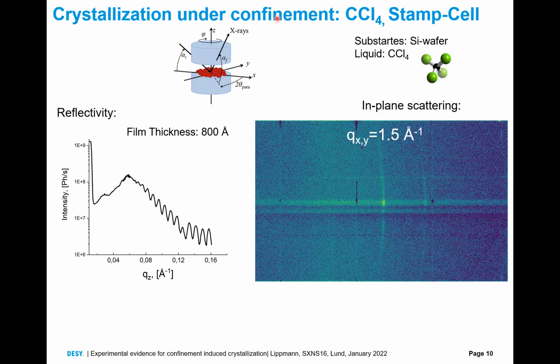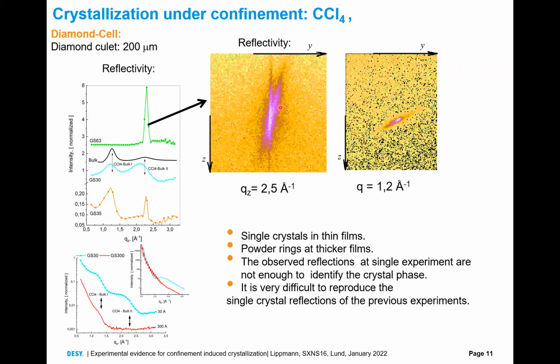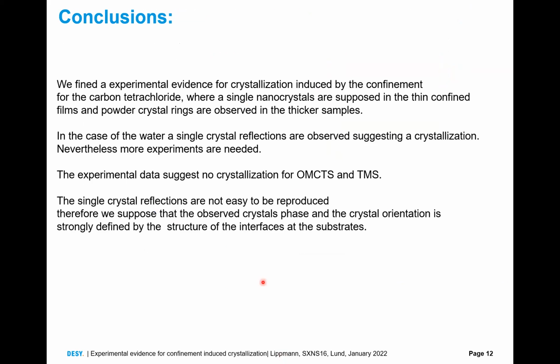About the carbon tetrachloride, we have studied this extensively, and we found out that it crystallizes in rings if we have thick films. It crystallizes in powder if you have thick films. And in the case of thin films, we observe single crystal reflections like in the case of water. With this, I come to the conclusions that we are pretty convinced that carbon tetrachloride can crystallize in confinement. In the case of water, we also observe single crystal reflections, and we believe that water is crystallizing in confinement, but we would perform more experiments about this.